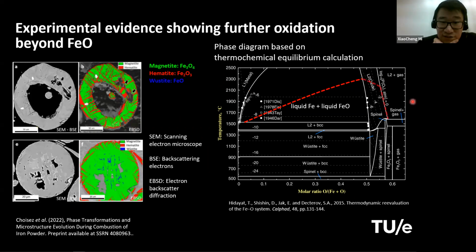And then later, beyond this point, the particle can get further oxidized. So the FeO stoichiometry is here, right? It's nearly at this boundary of this phase diagram, and the particle can be further oxidized until at some point it reaches this line. This line is the boundary or the limit of oxygen saturation, the oxygen solubility in the particle. So if you reach this line, that means no more oxygen can be dissolved into the particle, and it has to cool down because there's no way to absorb more oxygen and no way to generate heat through the oxidation.